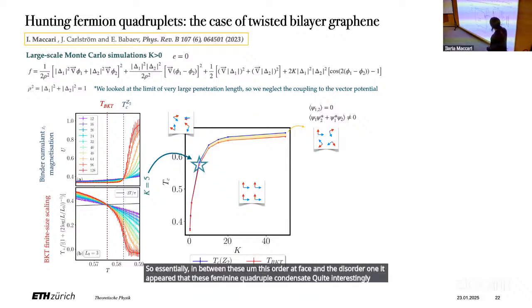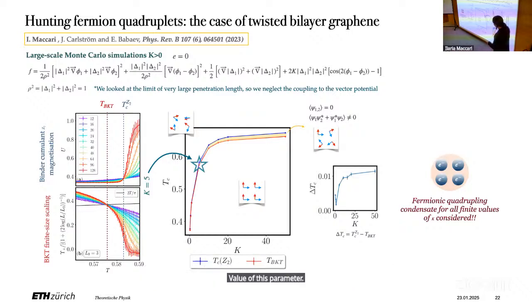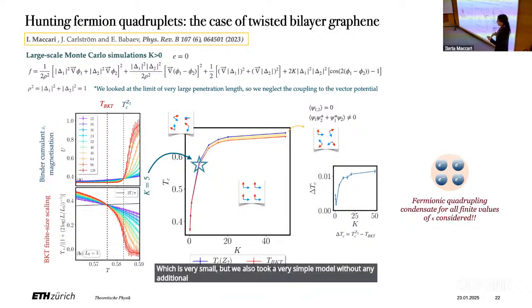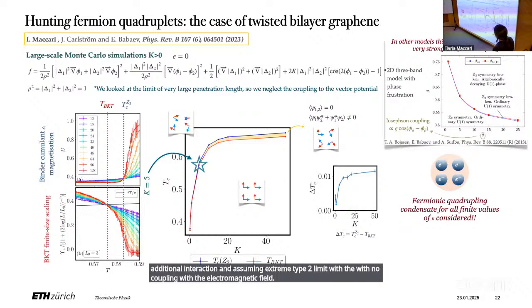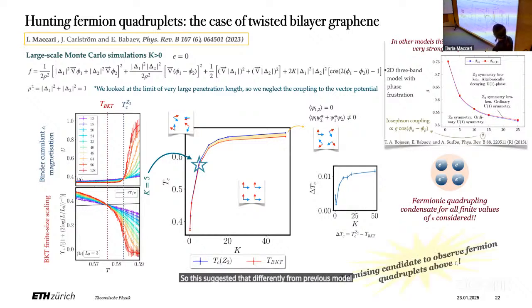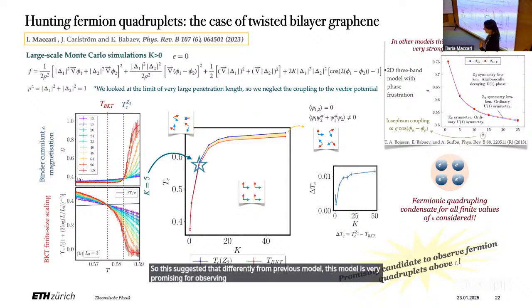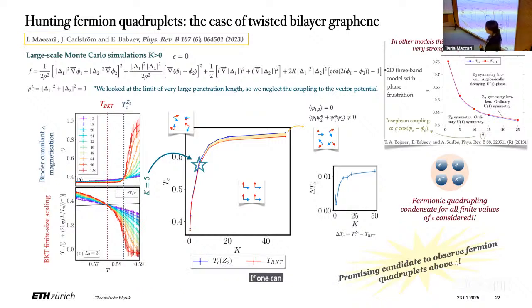Quite interestingly, we also looked at different values of K, and we could always find a splitting between the two transitions, which is quite rare, even for very small values of this parameter. So this is the difference in Tc, which is very small, but we also took a very simple model without any additional interaction and assuming the extreme type 2 limit with no coupling with the electromagnetic field. So this suggests that, differently from previous models, this model is very promising for observing and detecting these new phases. Maybe it is not a good model for magic angle twisted bilayer graphene, maybe yes, but it is worth looking at systems that can be well described by this model and seeing if one can observe a signature of this splitting.